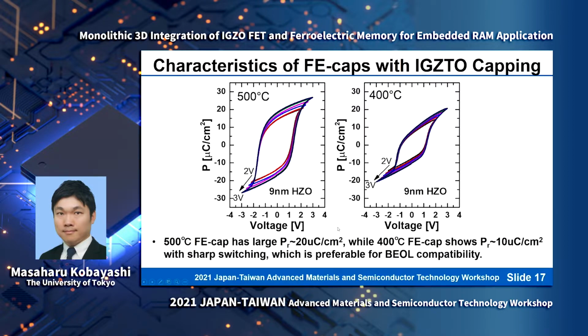Moreover, previously we only demonstrated a 500 degrees C ferroelectric capacitor process, but this time we were able to demonstrate a 400 degrees C ferroelectric capacitor. This is very promising for back-end process compatibility, because 400 degrees C is the minimum temperature that can be applied for the back-end process. So we were able to achieve fairly large ferroelectric charges and also very sharp switching with the IGZTO capping.